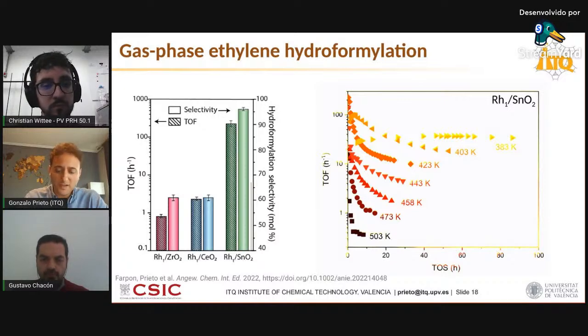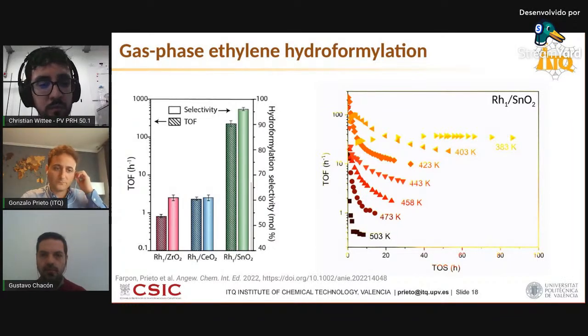So in short, the answer is we have tried some methods, but they are all based on disrupting and redispersing crystallites, because we believe that only that way the bonding to the support is strong enough so that the atoms remain isolated even under reaction conditions, if these reaction conditions are not very high temperature and very reducing. Perfect. Thank you very much.